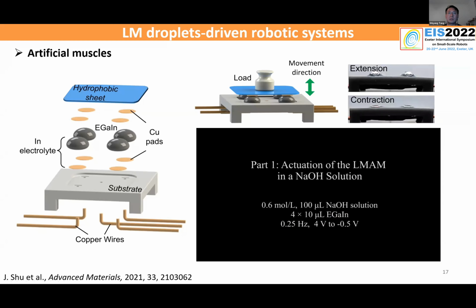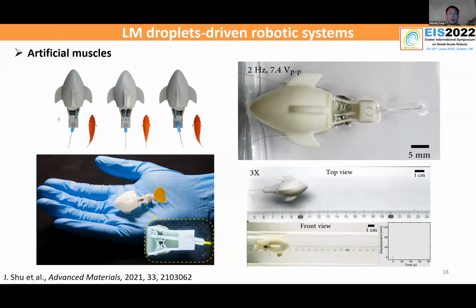So using these kinds of liquid metal artificial muscles, we use it to drive the caudal fin of a bionic fish. So I think this footage shows the story. Simply using 2 droplets, we're able to actuate the caudal fin at different frequencies, but we found that at 2 Hertz, it actually gives the best propelling efficiency.